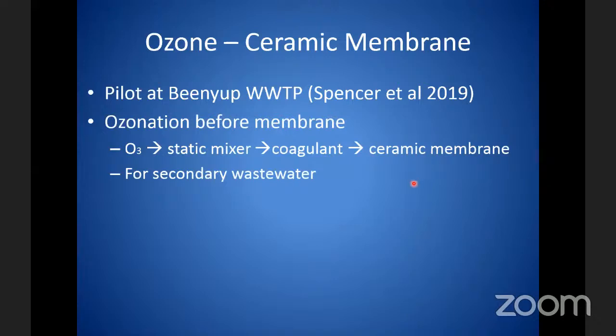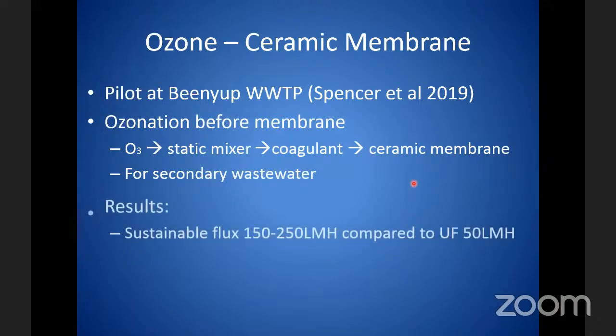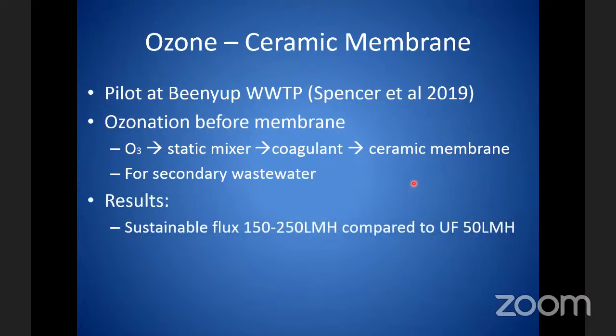So this is for secondary wastewater. The results found that they can increase the flux. With the ozone, they can increase the flux into this range, that means 150 LMH to 250 LMH, where UF is normally designed at 50 LMH.